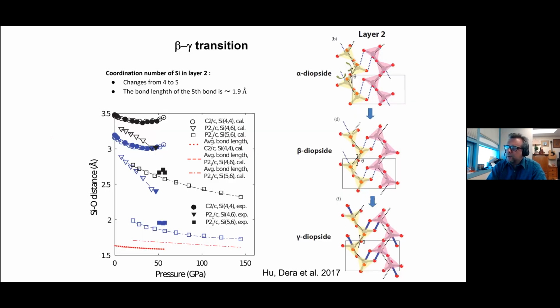So the mechanism of this transition is again consistent and similar to what we observed for enstatite, and shows that in this particular family, in the family of inosilicates, you can use pressure to reversibly change coordination number and reach coordination states such as 5 coordination for silicon.